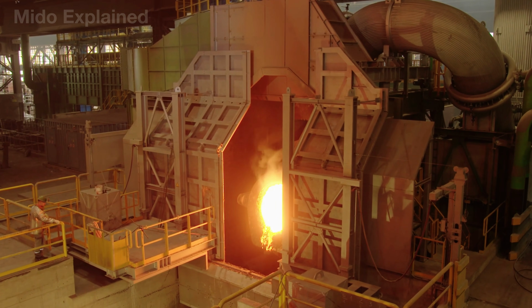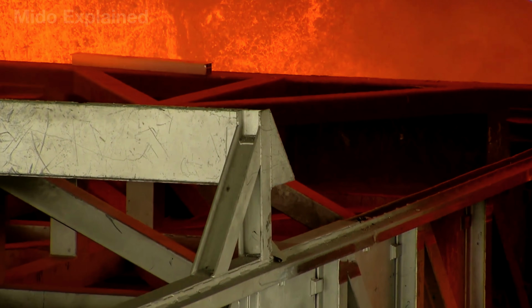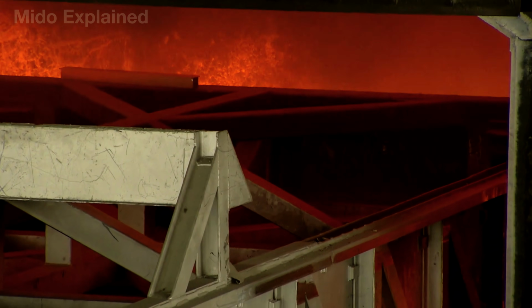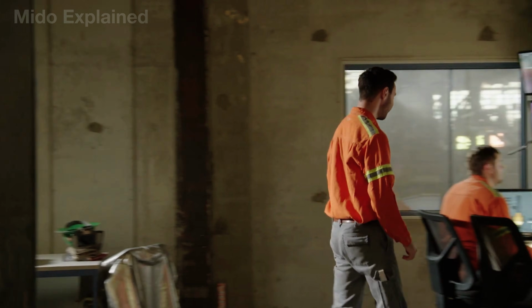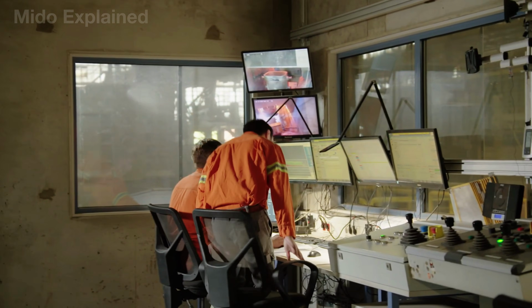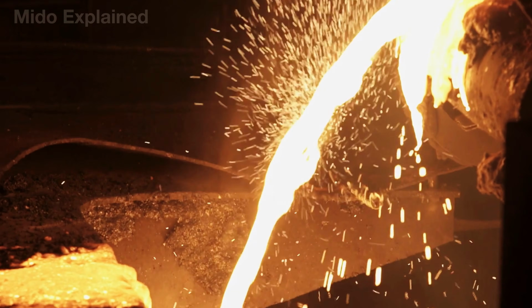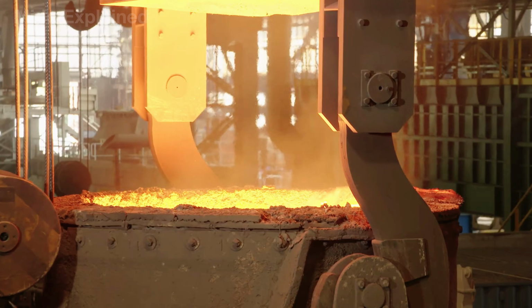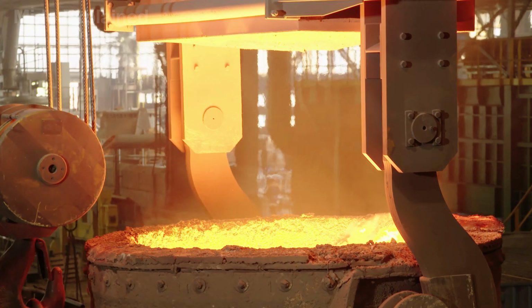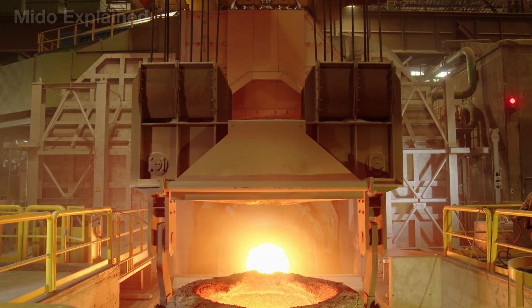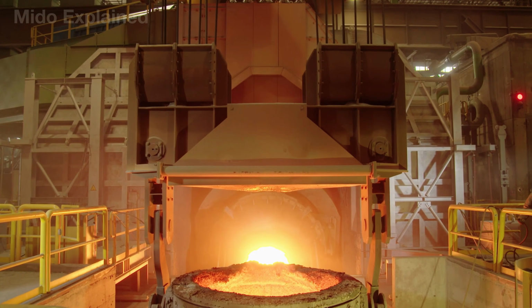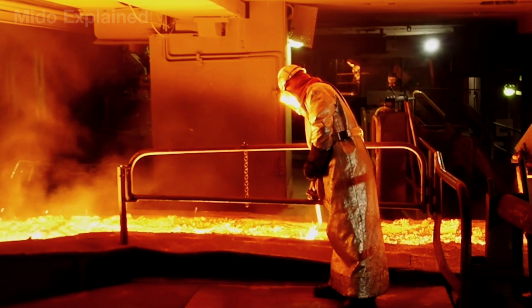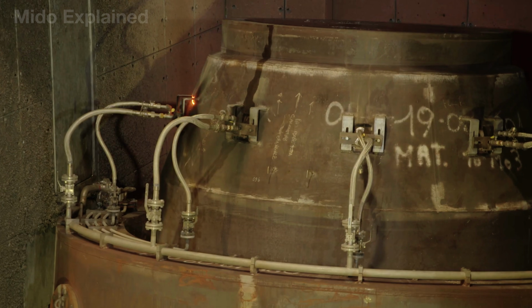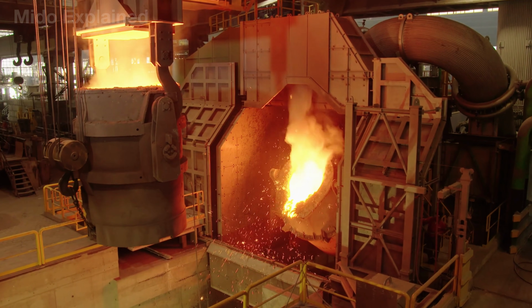This process typically lasts from 45 to 90 minutes, depending on the type of stainless steel being produced. The main goal of this step is to remove carbon without losing chromium, the crucial element that gives stainless steel its corrosion resistance. Once the carbon content meets the requirements, engineers begin adding precisely the necessary alloying elements such as chromium, nickel, and sometimes molybdenum to increase corrosion resistance.